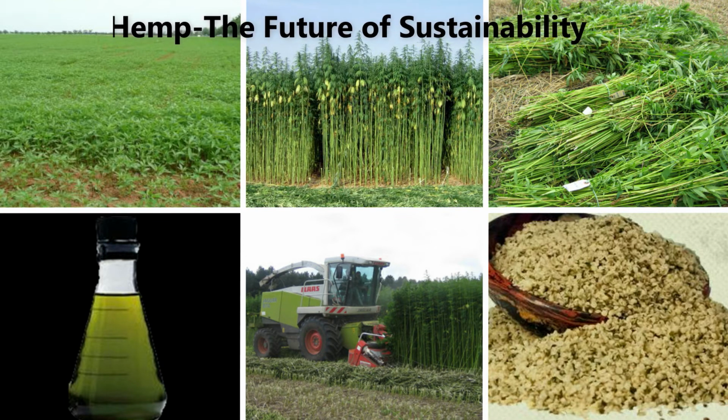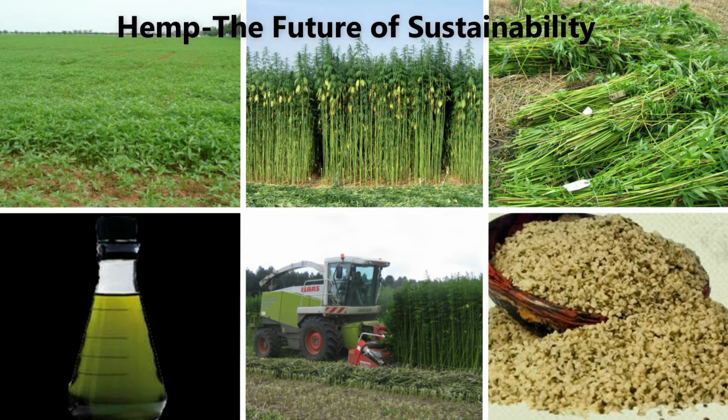That big bale then goes to a processing machine, put on a conveyor belt that goes into a first machine. And the equipment we have here is built by a Swedish company. There's a big razor blade that comes down and chops the bale into smaller pieces. And that then goes through a series of combs and rollers and needle punch machines to essentially, at the end, what comes out is a mat. And it kind of looks like stiff cardboard. It's about 1/8 of an inch thick. And it's essentially a random placement of the fibers at a uniform thickness and a uniform surface finish. So we can then take that mat, put it into the molds, infuse the resin, and make the parts. So it's essentially that simple.